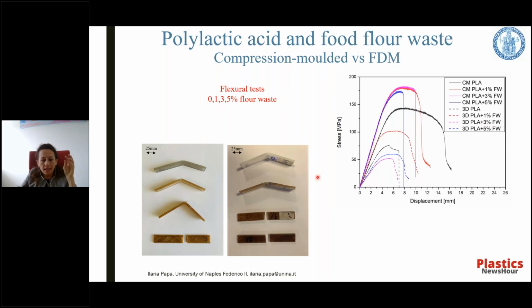Static and bend tests indicate also in the breakage that the failure in all composite systems tested occurs due to the activation of the compression failure mechanism on the upper surface of the specimen, and this behavior in the case of the 3D printed samples obtained with 1% of filler weight helps to overcome the limits of the technology by compressing the presence of voids in the section. However, as the filler content increases, the non-homogeneous distribution of the filler leads to a worsening of the mechanical behavior of the material.